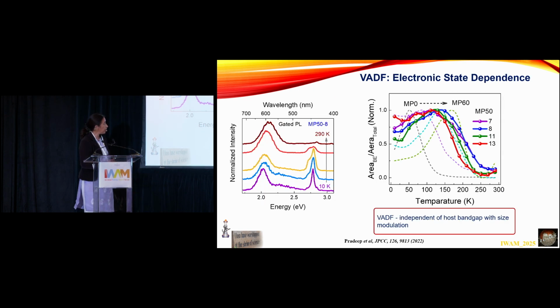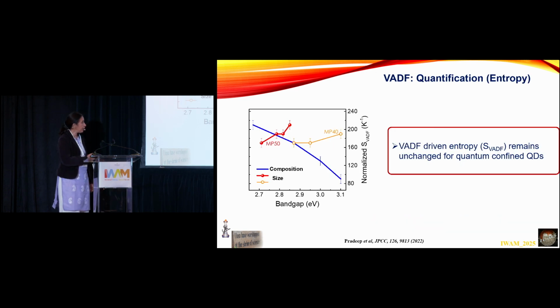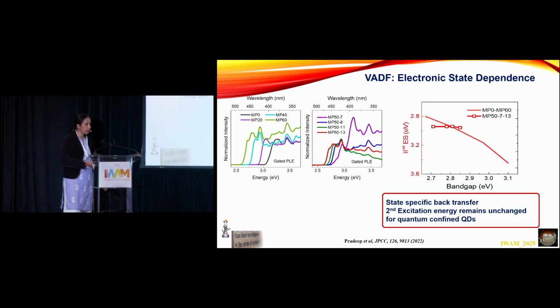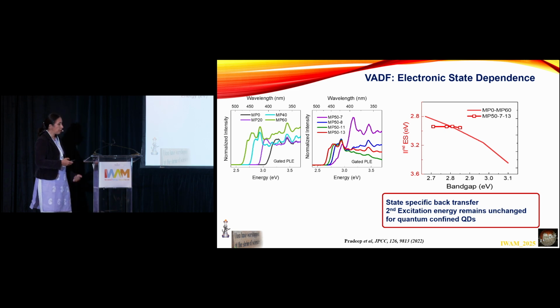So when we did look at the origin of these things using PLE, basically this is how we were observing the variation in the band gap. You see that for composition it changes like these dotted lines, but when I change the size it is one and the same. So what we did was trying to get this mechanism through energy, and we look at the PLE, which is the excitation which basically gives rise to this delayed emission. So we looked at the gated PLE to see where this is coming from.